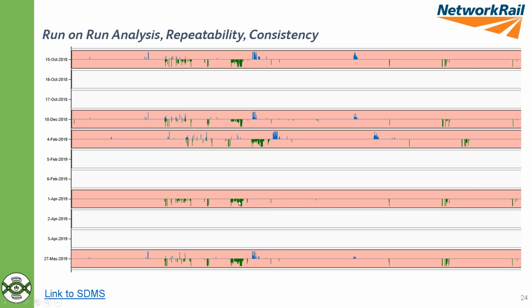One of the other things we must be careful of is this April run here, where the left channel ultrasonic eddy current failed, so there were no results recorded. Because it effectively only reports where it thinks there's RCF, you have to be very careful that you understand whether it's been tested, or whether you think there's no RCF when actually it's just not been tested. That's some of the challenges we've been having at the moment: how to get this positional accuracy more consistent and not have this variation in mileage, which can make a site appear to disappear or reappear. In actual fact, we've got to find a way of doing this.